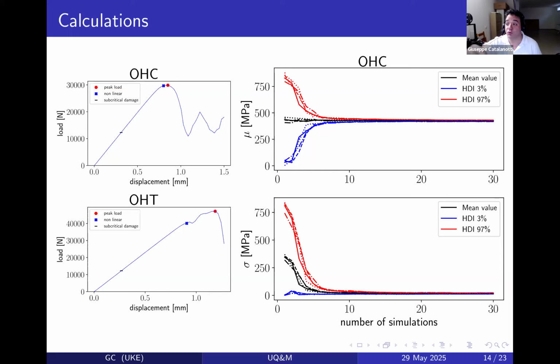I compute the hyperparameters of my distribution. In this case, the hyperparameters are the standard deviation and the mean value. And as you can see, this high density interval represented there shows that at the first simulation, I actually don't know where I am, because the interval might go from 50 to 800. I'm talking of the plot that is on the top.